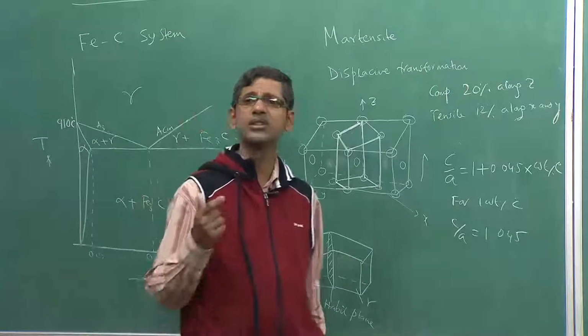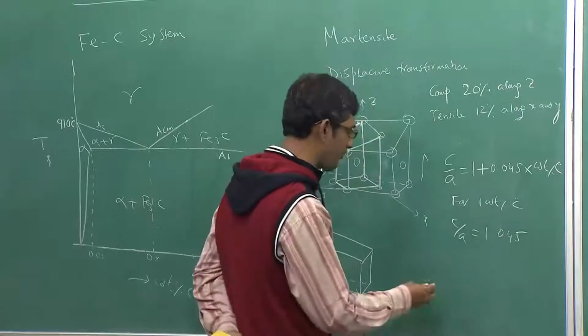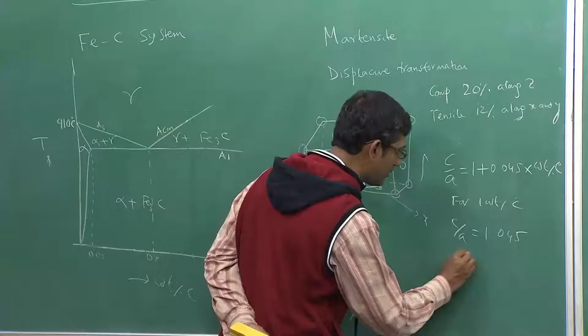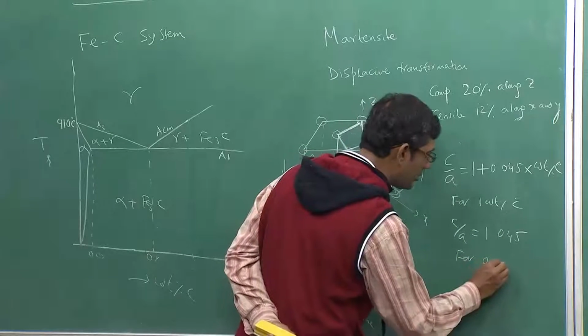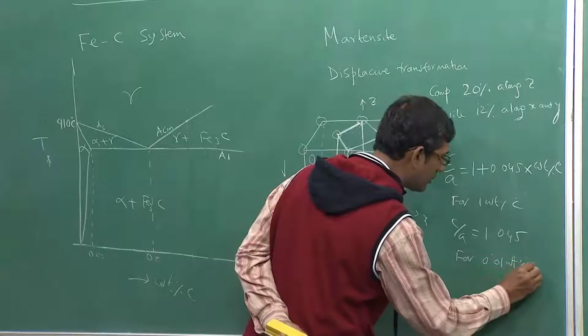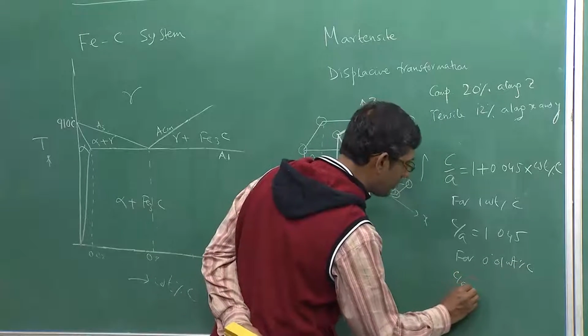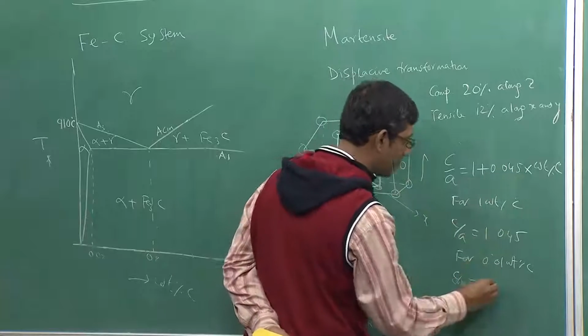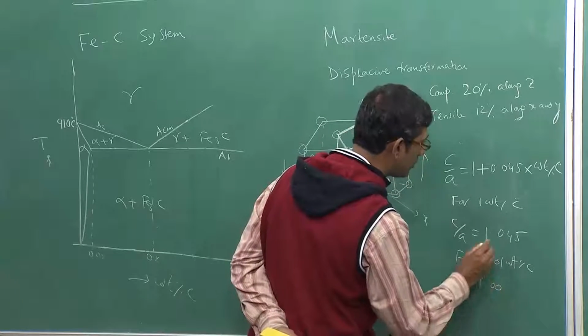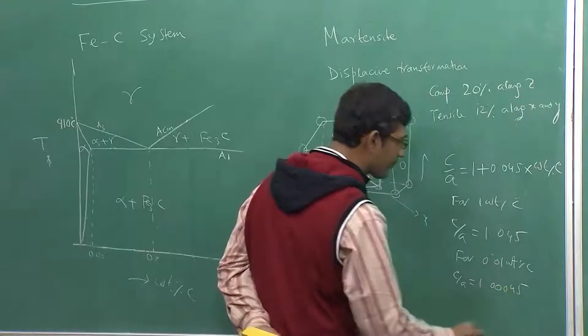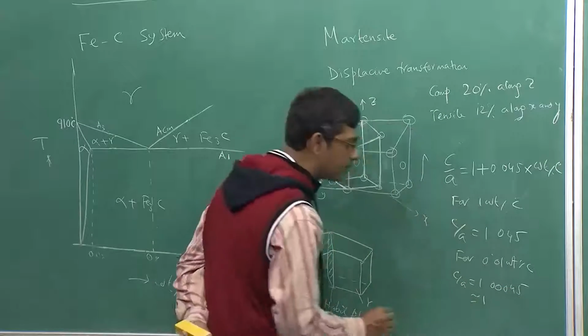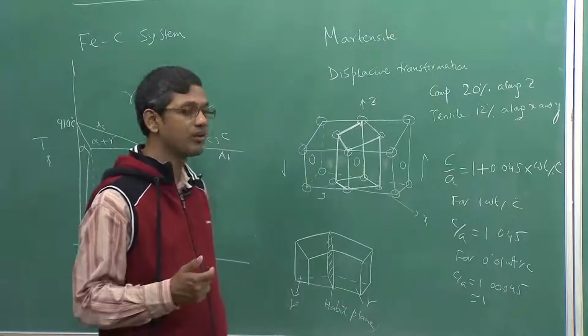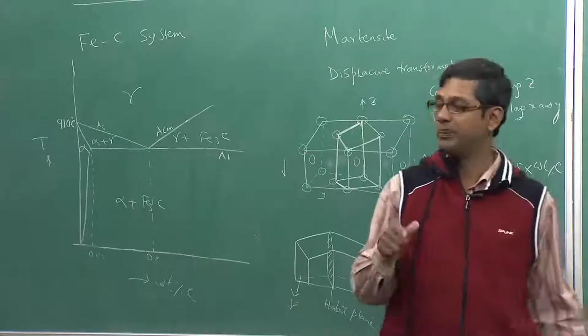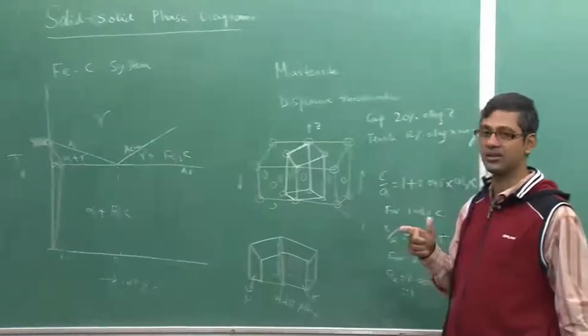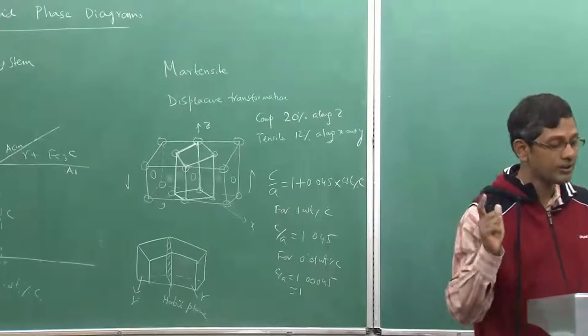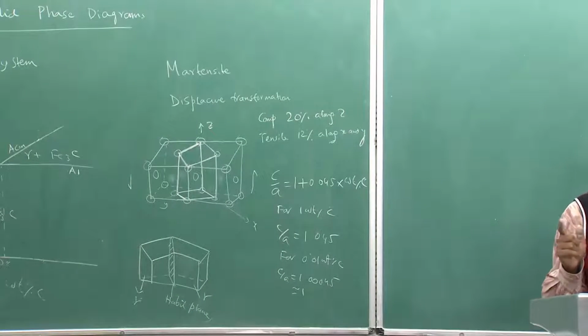So, if your carbon concentration is very low, suppose carbon concentration is 0.01 percentage or 0.05 percentage, let us calculate it. For 0.01 percentage of carbon, the C by A is basically 1.00045, that is nothing but 1. So, that is why for very low carbon concentration steel you produce a BCC structure, not a BCT structure, that is, body centered cubic, not body centered tetragonal. That is one thing you must remember.